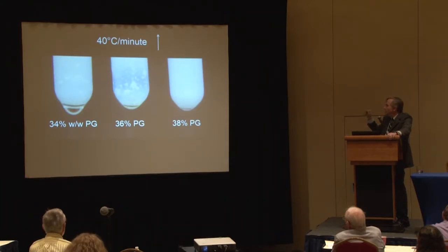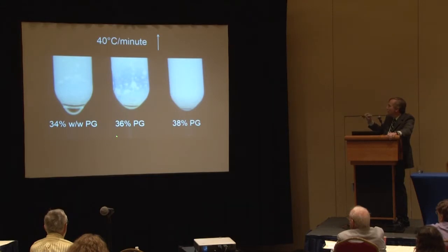I was actually able to demonstrate this in the laboratory on the first try. These are 3 different concentrations of propylene glycol. This is hard to do at slow cooling rates, but I managed to do it. And you can see that this solution is pretty milky. It's because it's just barely vitrifiable. It's actually basically unvitrifiable. And this solution devitrified to an opaque state during rewarming.